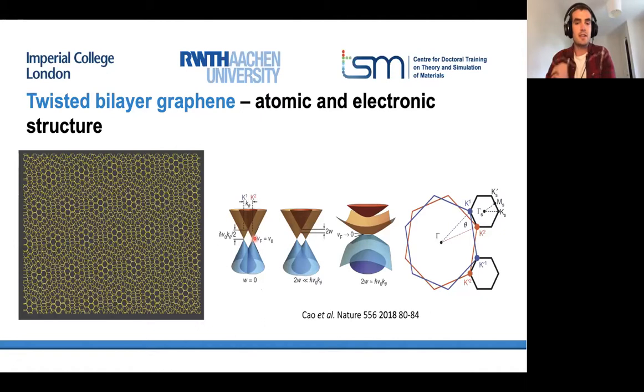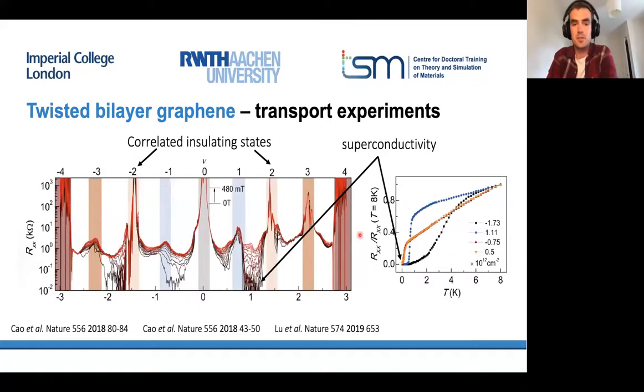And because these graphene layers can hybridize with each other, when the momentum misalignment between these two Dirac cones matches the hybridization energy between the layers, you can get the emergence of extremely flat electronic states at the Fermi energy. And when that happens, the electron interaction energy becomes the dominant energy scale of the system. And as we know, we get the emergence of broken symmetry phases.